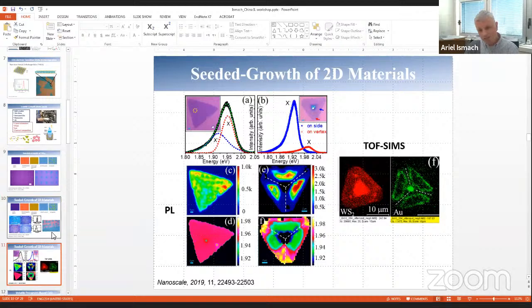But in this case, you need to be careful because some of the metal seeds might affect both the crystallinity and also the chemical composition of the TMDs, in this case MoS2 or tungsten disulfide. As you can see here, for example, from photoluminescence maps, we can do mapping of PL of these domains, and we can show that there is a strong correlation with the presence of gold. This is by TOF-SIMS, so this is a chemical mapping, and this is a photoluminescence mapping.